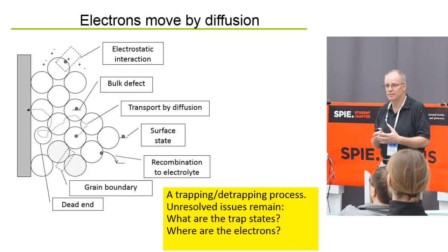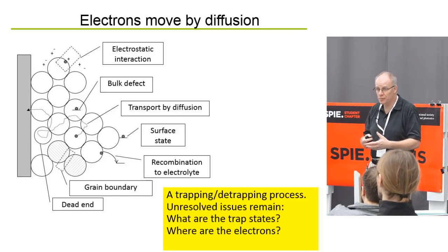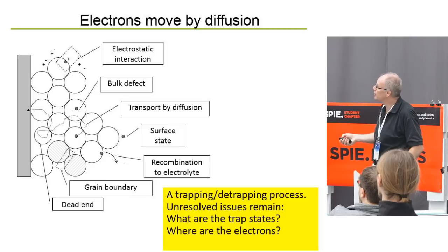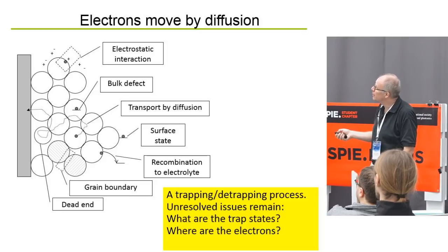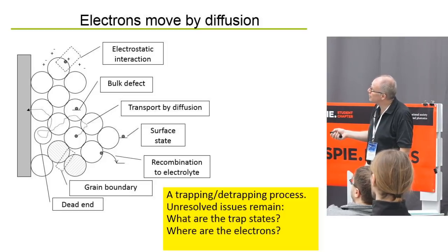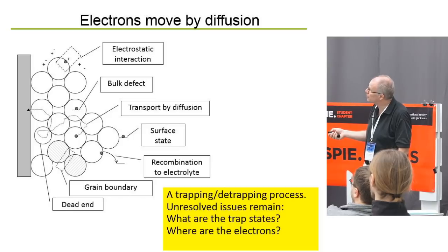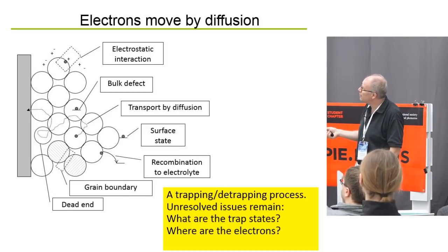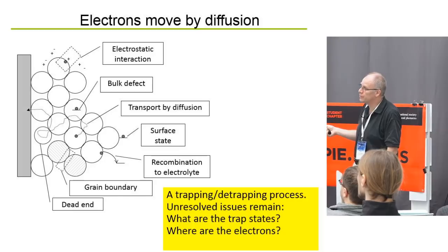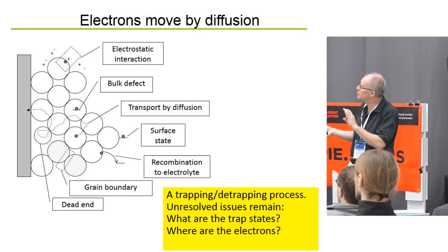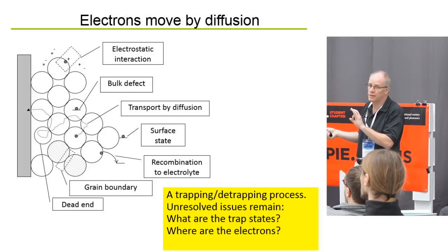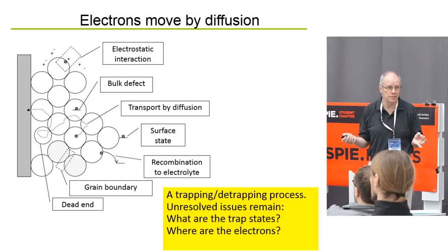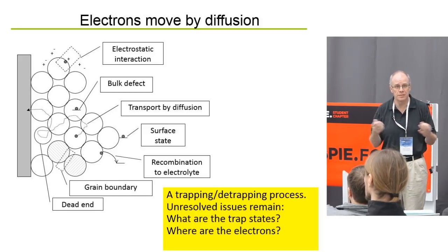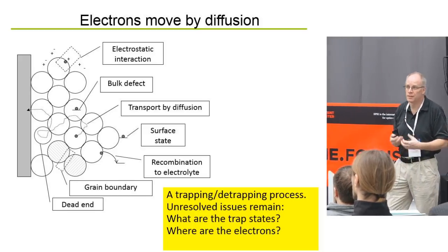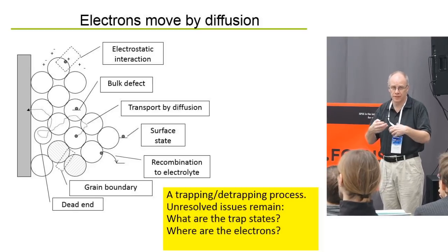If we just think that the charges are actually going to the contact, and then they are taken out at the circuit, that means that the concentration of electrons is lower at the contact, where we extract them, than the concentration of electrons in the film. There's a higher electron concentration in the film than at the contact. That means a concentration gradient, and that is diffusion. So we said this is based on diffusion, not on electric field.